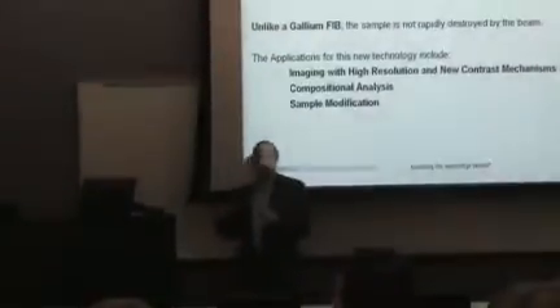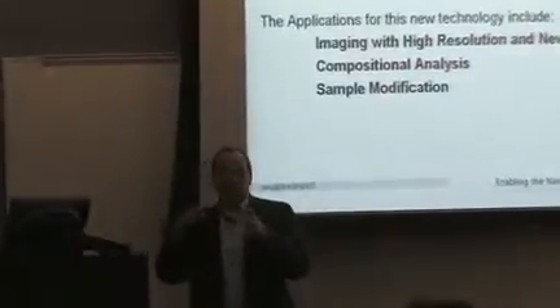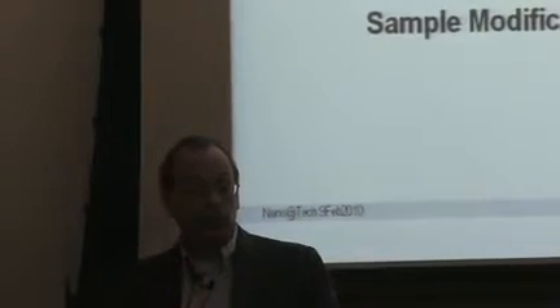So for the elemental analysis using the backscattered helium, what's the spatial resolution? Maybe you said this. The lateral resolution. Yeah, that is definitely limited. You're guessing it's limited because it goes underneath and can scatter some distance away. Exactly. That's one of the mechanisms that can certainly limit it. The helium ion beam will diverge. The helium atom goes underneath the surface and scatters out. So that would limit you to perhaps 10 or 20 nanometers.